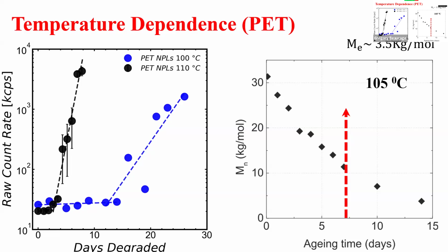Why is that important? I also put up there the entanglement molecular weight for PET, which is about 3.5 to 4 kilodaltons. I told you that the fragments are related to the crystal size, right? Why am I bringing up entanglement here? If you take an amorphous polymer and go below the entanglement molecular weight, the whole thing becomes fragile and falls apart. So even though this is degrading at 7 days when it makes micro nanoplastics, the molecular weight is too high for it to be unentangled. It's high enough that the stuff is still highly entangled. So it's not an entanglement issue, it's something else that's driving it. That makes sense? Or have I lost you?